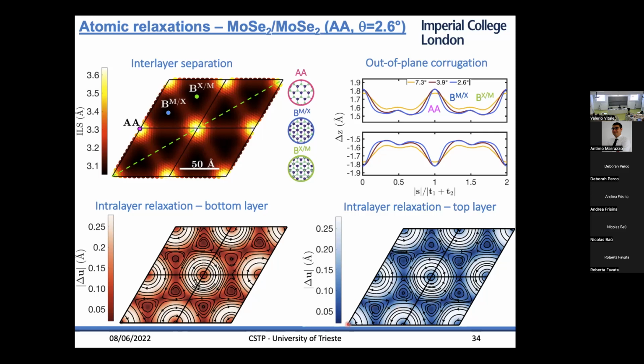Question. Can you study this relaxation for larger angles and smaller samples, but with DFT? Yes. Can you check in the case that the effective model that you're using is reproducing the same thing? So these models are very good up to certain angles. Things go quite badly below 1 degree, where you have these strong relaxations. So the DFT level and the classical force field diverge below 1 degree.